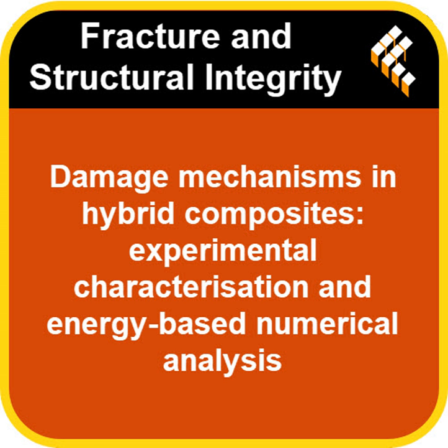Fascinating. And finally, how did the layers peeling apart, the delamination, differ in those two key hybrid configurations? They saw similar initial delamination damage starting near the last carbon layers for both setups. However, the 6C2G sample, the one that didn't have glass on the compression side, experienced much more severe and widespread delamination. When they looked at the simulation at the point of maximum bending displacement, they even saw visible separation between the glass and carbon layers in that 6C2G configuration, as well as between the initial carbon fiber layers near the tension side. It peeled apart more dramatically.